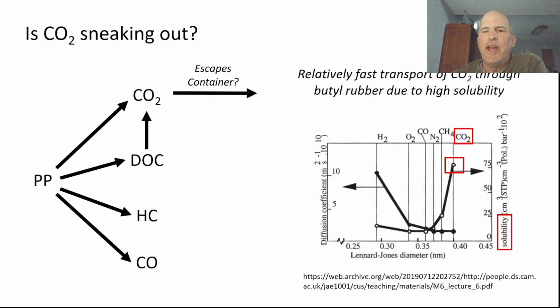If they get a flat, they fix the flat, they would have these air cartridges, but it wasn't air in them, it was CO2. So they would fill up their repaired inner tubes with CO2, they'd ride it home, and the next day, without fail, it would be flat again. And so that's how this discussion online came about, is these cyclists asking, why does my tire go flat? And the reason was because CO2 slowly diffuses through the butyl rubber and escapes, and that's why it goes flat.